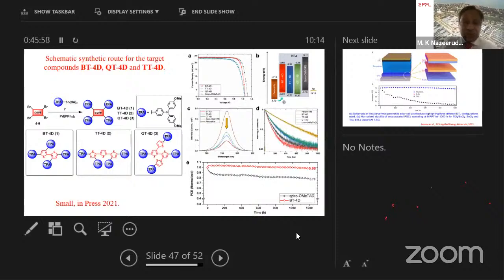But if you look at the stability data of this molecule, this is BT4D. The data is shown here. Over 1,200 hours, the initial efficiency remained at 98%. Under similar conditions, the spiro efficiency decreased to 79%. So these are the types of hole transporting materials the students can think of for coming up with the new molecules.